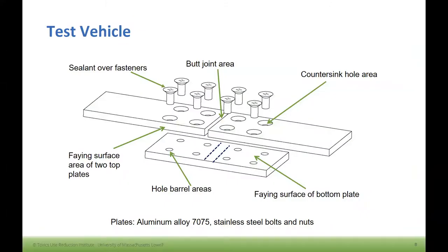And we needed a test vehicle to do the evaluation. What we have for a test vehicle is three aluminum plates that are brought together and fastened together with six fasteners and six bolts. By doing this, we create a number of different opportunities for evaluating sealants. We create a faying surface, which is when you've got two surfaces sandwiched together, so it's basically the surface in between. We've got a butt joint area, which is when you've got two surfaces that don't quite close the gap and there's a gap. The sealant would go in there. And also we have fasteners, and we apply sealants over the fasteners to try to prevent any penetration to the fastener area.